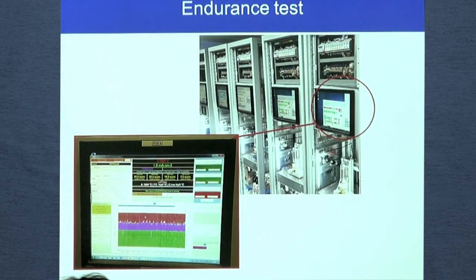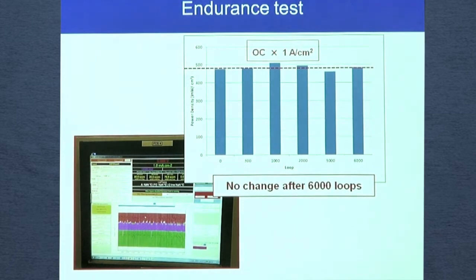Okay. Of course, the question is durability, because it's one of the main parameters. We can perform heavy-duty endurance tests using fuel cell testing stations with the possibility of cycling and programming accelerated tests, and you can see that even after 6,000 loops between open voltage and 1 ampere per square centimeter, we have almost constant performance of the catalyst. The catalyst is very stable, mainly if we use the nitrogen-doped carbon as a substrate.